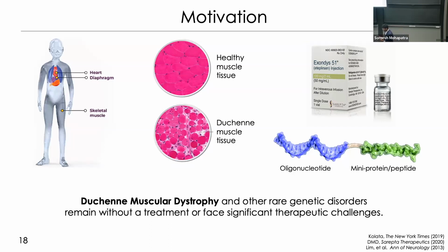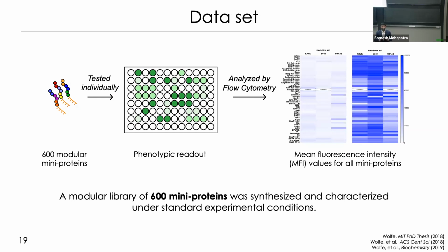So we looked at the data set. Thankfully, very painstakingly, an entire data set of 600 modular mini proteins was put together by students at Brad's lab, Justin Ulf and Colin Fadson, where they had mapped each of these 600 modular mini proteins to their phenotypic readouts by testing them individually and had a number referred to as mean fluorescence intensity for each of these individual sequences. So 600 sequences, each sequence had a number associated to it on a scale of 1 to, let's say, 20, which was the maximum of the range of the training data set, which said how much better each of these sequences performed as compared to the drug alone. So if it is 20, it's a 20-fold improvement in terms of delivery.